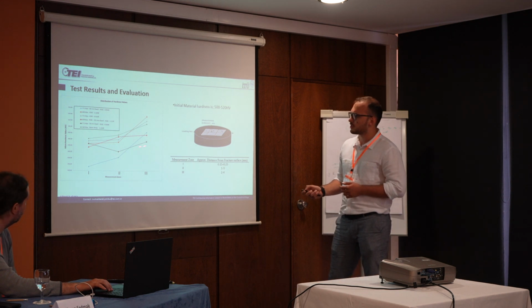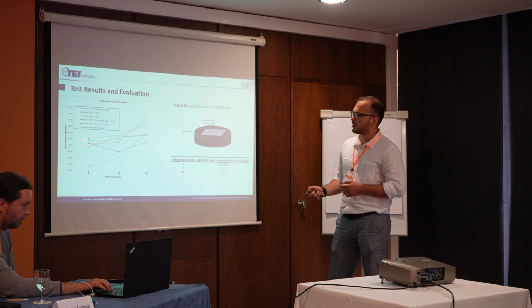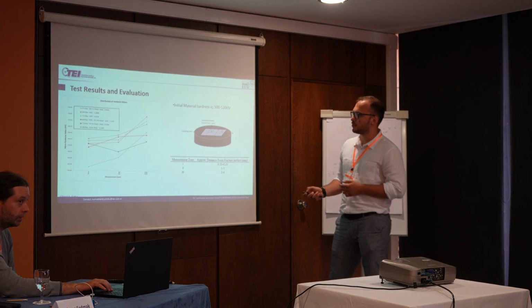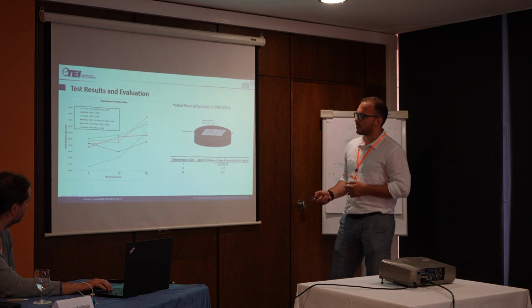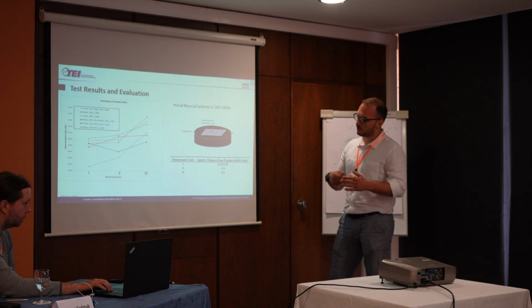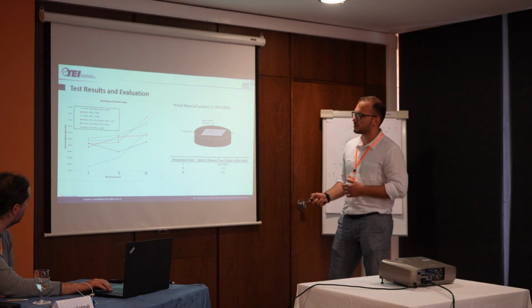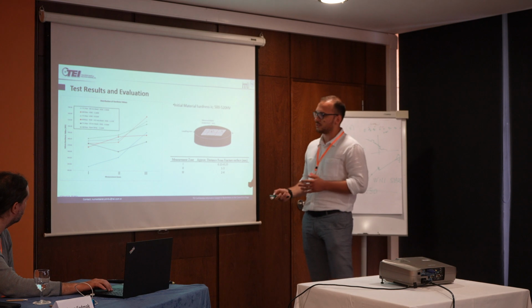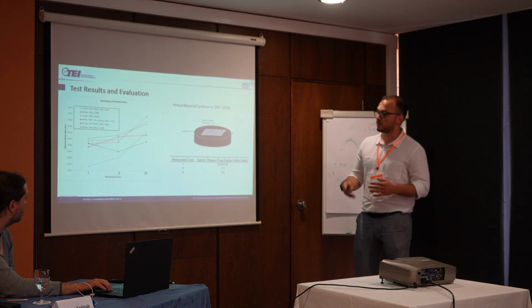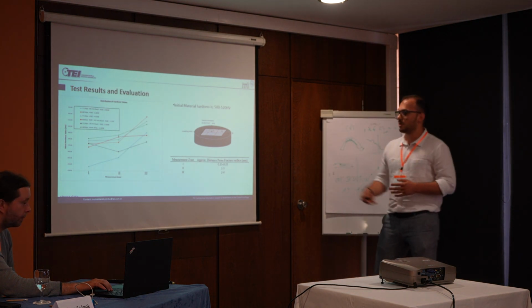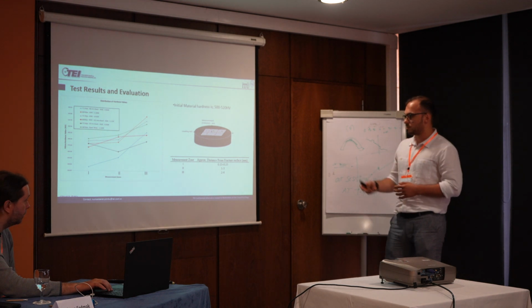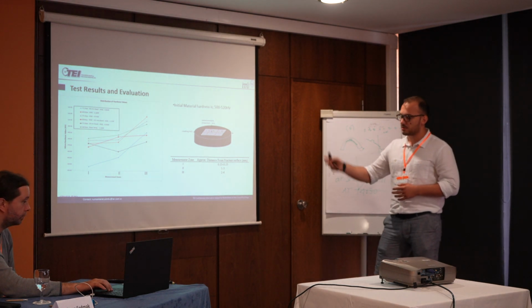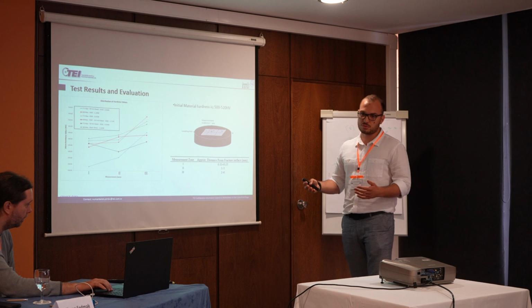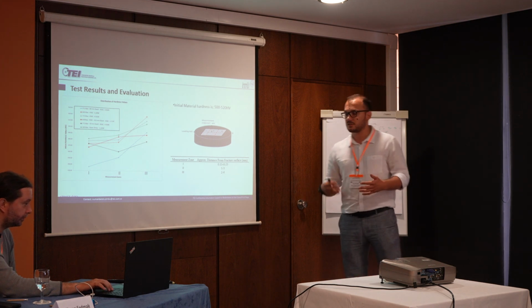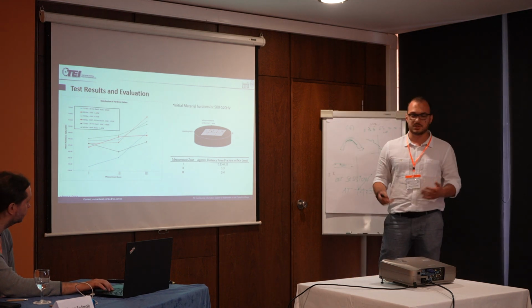Sorry, this one's the full cyclic, and this blue one is a dwell at the same stress values. But it seems that once we reach the fracture surfaces, the dwell fatigue one has much lower hardness values than the other. So once we see that, we just want to learn about the plastic capability of the specimens.